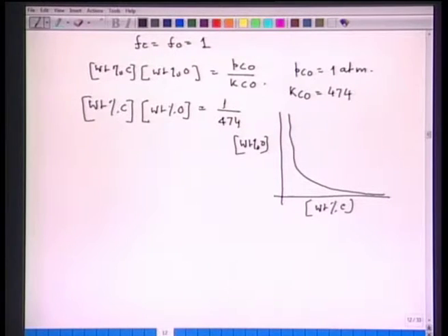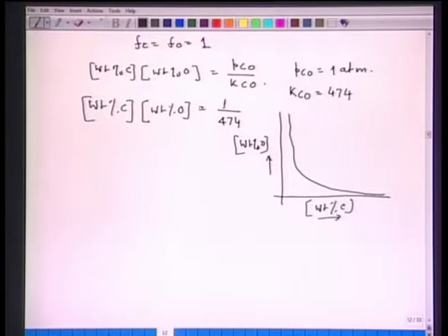This is just a schematic relationship. So, weight percent carbon increases from here and weight percent oxygen increases in this direction. What this plot suggests is that as the weight percent carbon increases, the weight percent oxygen dissolved in steel decreases. Also, this plot suggests that at low percent carbon in steel, the dissolution of oxygen increases, because at the lower ranges of carbon, the dissolved oxygen increases very fast.